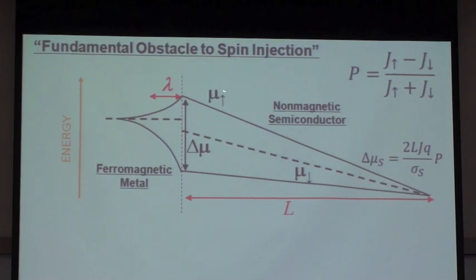So here we have an electrochemical potential for spin-up, and it has a high gradient, giving rise to a higher current than for spin down. And this then results in electrochemical potential splitting at the interface. Okay, now we can write down a simple expression for the polarization, which is just the relative difference between the current flow for spin up and spin down. And what we find is that it's a function of the splitting in the electrochemical potential at the interface.